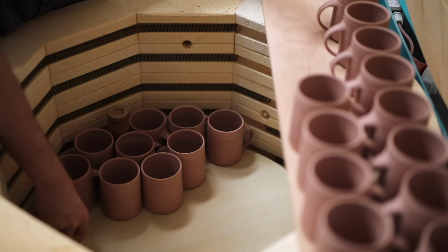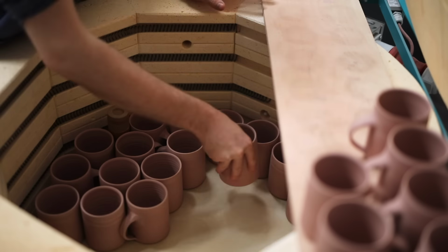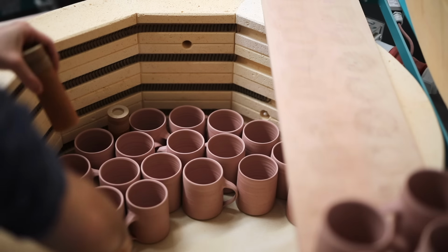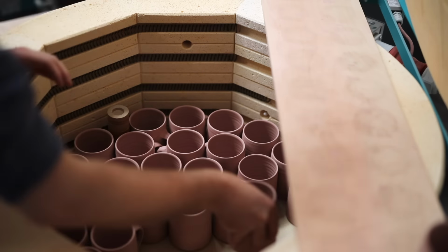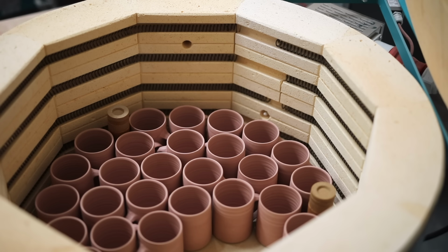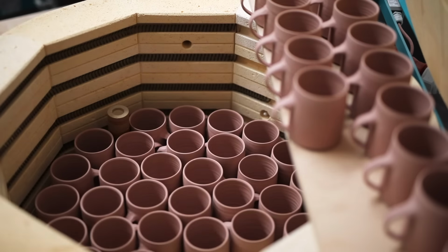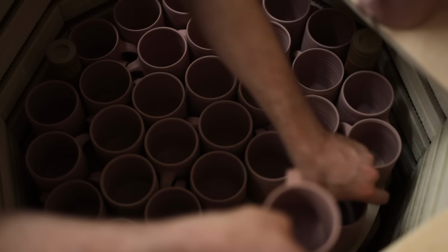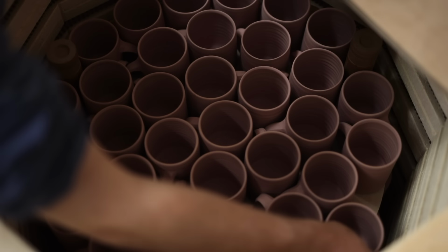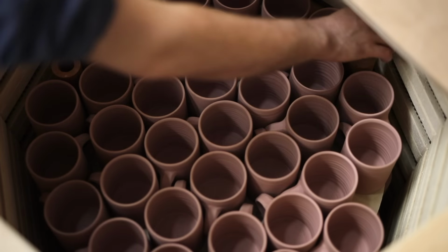This is all very delicate work though, as at this stage the bone-dry pots are incredibly brittle and fragile, but after being bisque fired overnight to 1000 degrees centigrade and having gone through quartz inversion, the pots become much stronger, and they also become absorbent too, which is necessary as these still have to draw in a layer of glaze later on. I fire my electric kiln overnight when I'm not in the studio, which is very different from my gas kiln, which I have to be with the entire time as I'm firing it. In many ways, I could also be doing all my bisque firing in my gas kiln too, but having an electric kiln means I get to do this overnight, when I'm not at the studio, which saves some time.